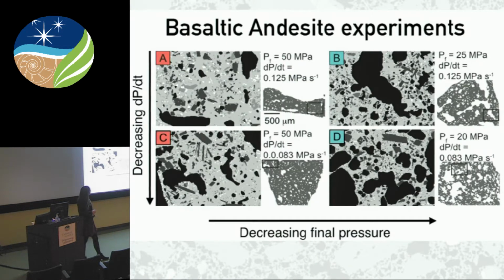Here are some segmented images where the different gray values represent the glass, which is a lighter gray, the darker gray, and I don't know if you can see the white specks in here, are all crystals that are forming in the experiments. And we see a wide range of crystal sizes and shape in all the experiments, and no particular change in shape between the different decompression rates.